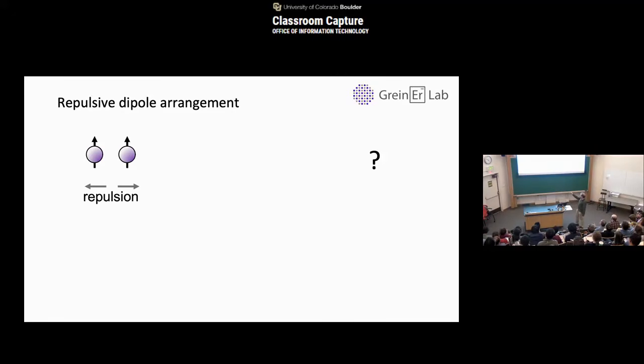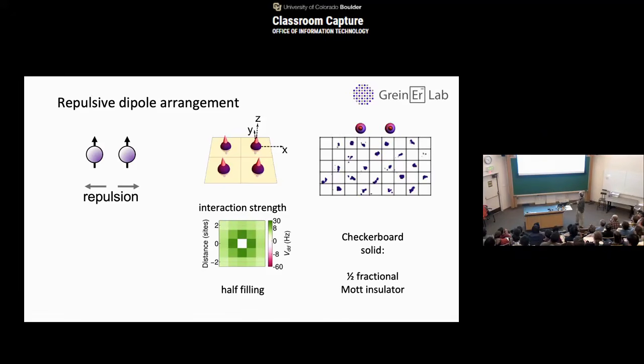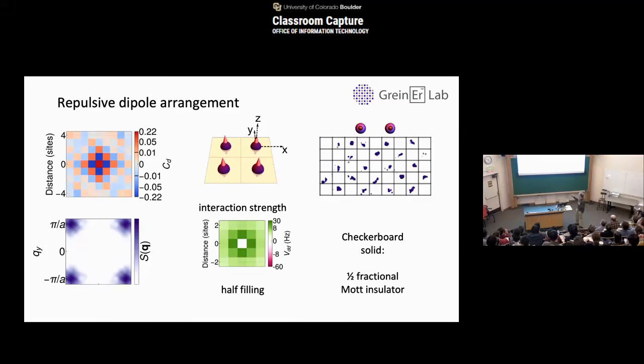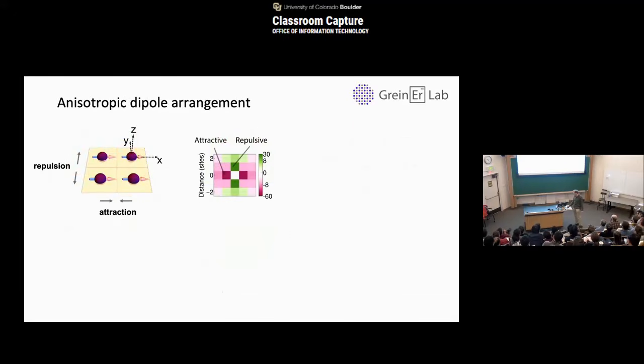If, after a lot of optimization, we have the dipoles perpendicular to the plane here, what happens? What do you expect, right? What kind of shape do you expect at half filling if you have repulsive interaction? Well, they don't want to be next to each other, right? At half filling, they should form a checkerboard. And in fact, that's what we see in these pictures. Oftentimes we get pictures that look quite nice, like a checkerboard. You see this is empty, and there's an atom, empty, atom, empty. It's not always this perfect. So on average, we get correlation plots like this, and this would then be the corresponding structure factor. But we can nicely get into this regime where the dipole interaction is really the dominant term.